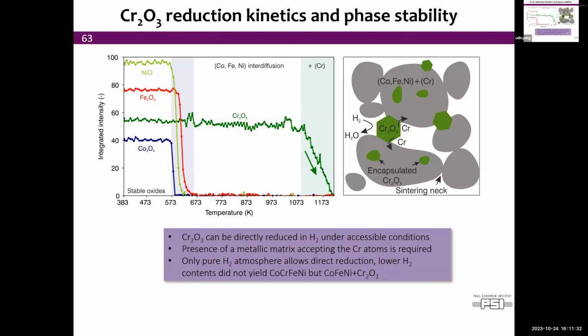So if we look now as a function of temperature at the intensity of those diffraction peaks, that is going to give you how much material is there. So we start with all the oxides with their original intensity. It doesn't matter what the value is. What is important is that cobalt oxide disappears first, then the nickel oxide, then the iron oxide. All of this at roughly low temperatures, right? Between 300 and 400 degrees C. They're all reduced, they interdiffuse, and they're in contact with the chromium oxide here. So here's our kind of pre-reduced cobalt, iron, nickel. And only at the highest temperature, the chromium disappears.